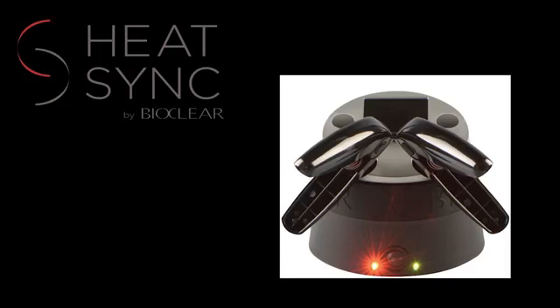So at BioClear, what we use is our Heat Sync composite heater, and the benefit of this compared to some of the other heaters out there is the volume of composite that we can heat at one time. It does maintain the temperature of the composite to 155 degrees Celsius, 155 degrees Fahrenheit, which we found to be pretty ideal as far as the change in viscosity of the composite. And it also has an oven to store more compules, which is a really nice feature especially when you're doing a lot of injection molding.